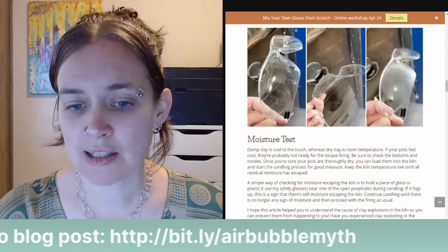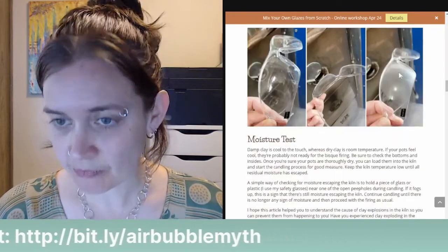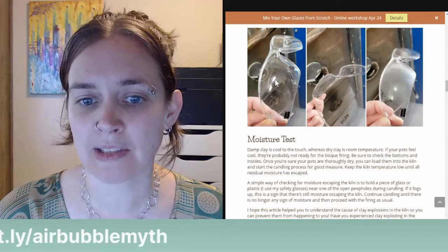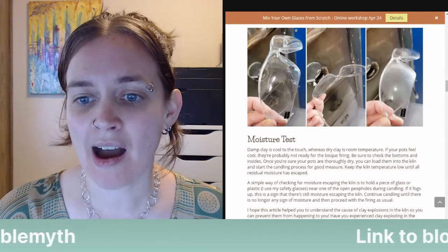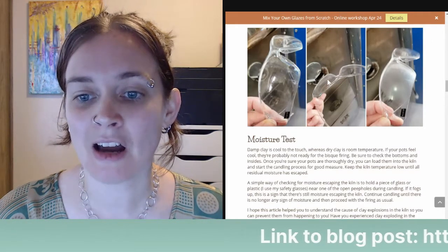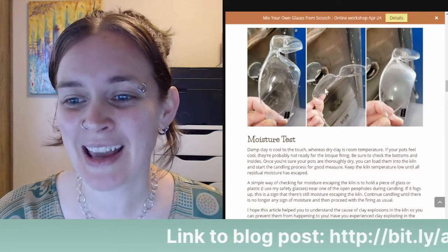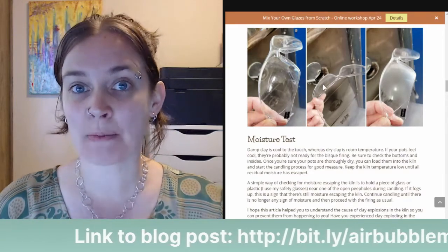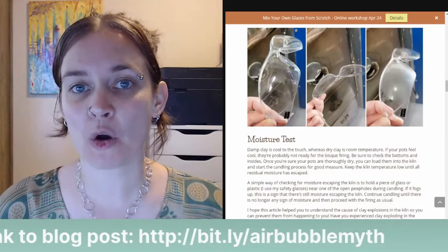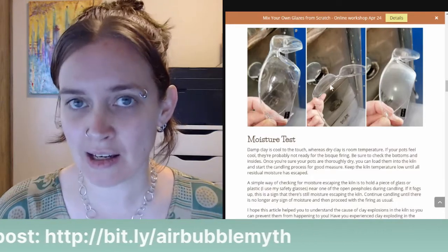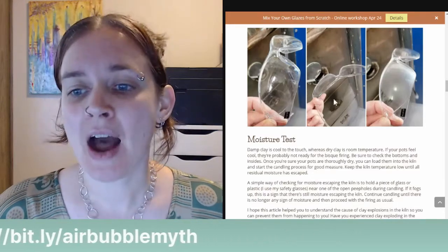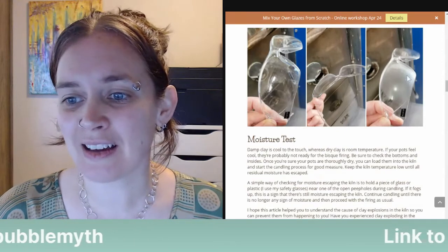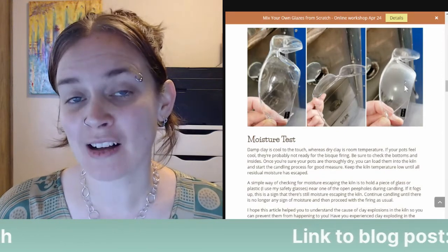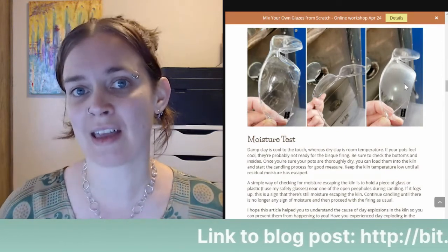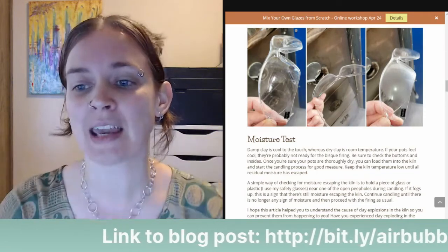So here you can see in this picture, I'm taking my safety glasses. I hold it up to the peep here, not too close. You don't want it to melt. This is during our preheat time where we're holding the temperature at 190 degrees Fahrenheit. And here you can see the glasses have fogged up. That is a sure sign that there's still moisture escaping the kiln.